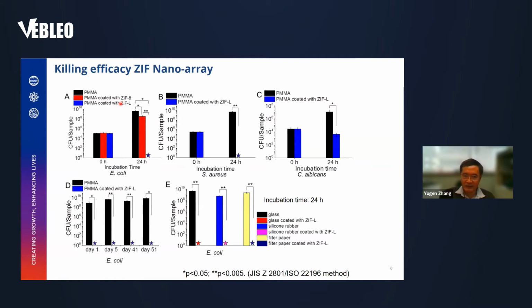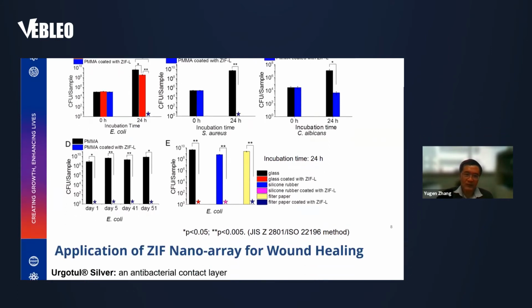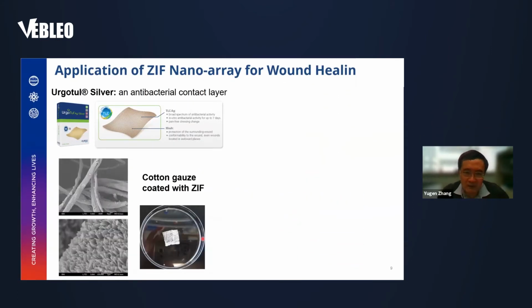This ZIF-8 and ZIF-L have the same chemical component, but you can see here, the blue one has excellent killing properties, but the red one basically has no killing. And similarly for the SA, also the C. albicans, they all demonstrate good killing, because we also try to challenge the coating surface repeatedly at different times, and they all give very good results. And also this ZIF coating on different substrates like glass, silicone, or filter papers all give very good bacterial killing properties.